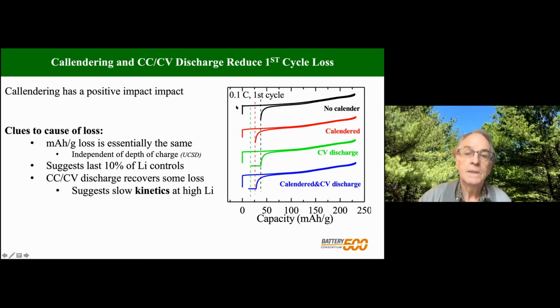So these are not important parameters. What is important is calendering, so we need better contact between the particles. Here in black is the effect of no calendering. You can see some calendering reduces this first cycle loss. We also found that after doing a constant current discharge, if we now go to a constant voltage discharge, we gain some of this capacity back. And if we do calendering and constant voltage discharge, we get even more back.